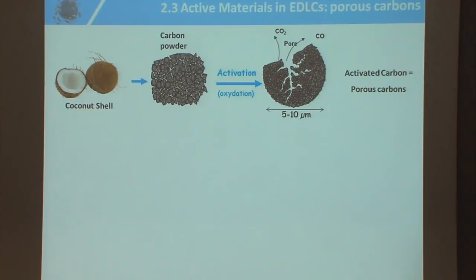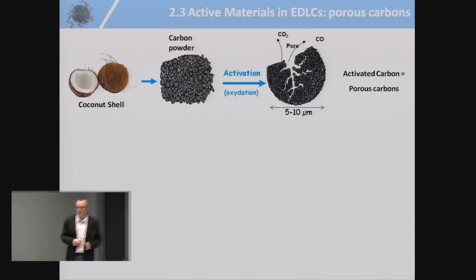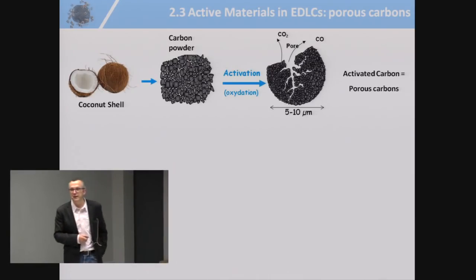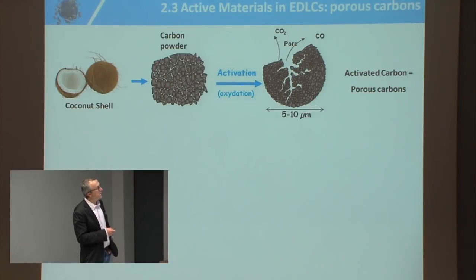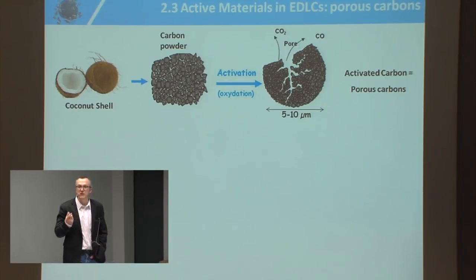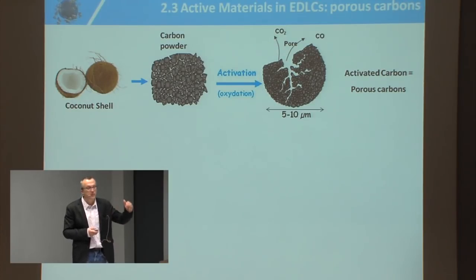Okay, now let's move to the carbon, which is the key part of the material of supercaps. I told you it was porous carbon. What do you do? You start from a coconut shell, which is a green precursor. And then you do a first carbonization, and you end up with particles of about 5 to 10 micron. And then you do what we call activation treatment. What is an activation treatment? It's a controlled oxidation of carbon into CO2. And then you end up with pores here.